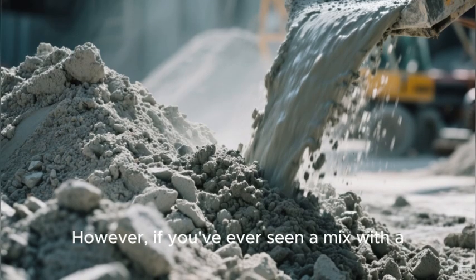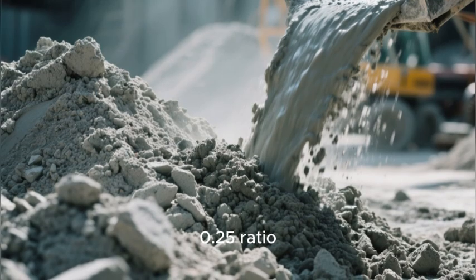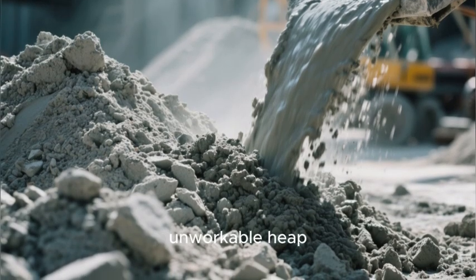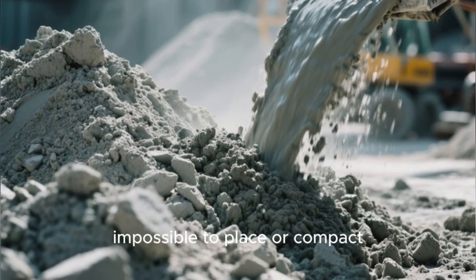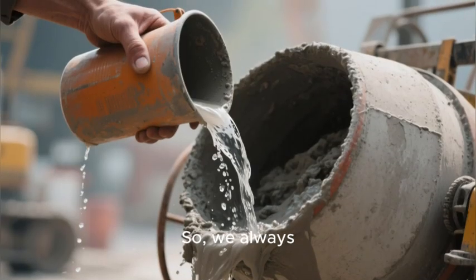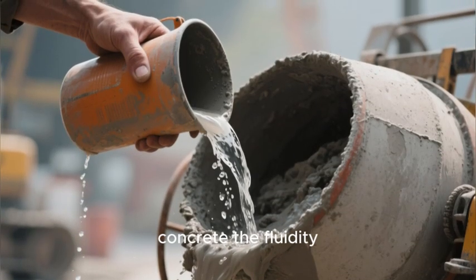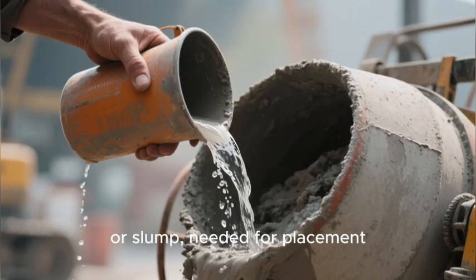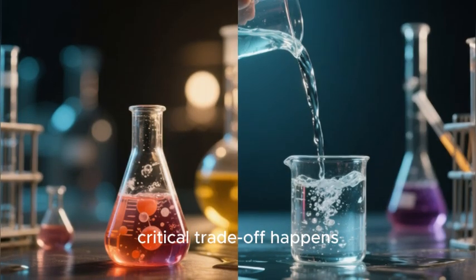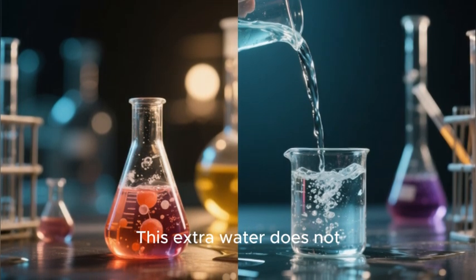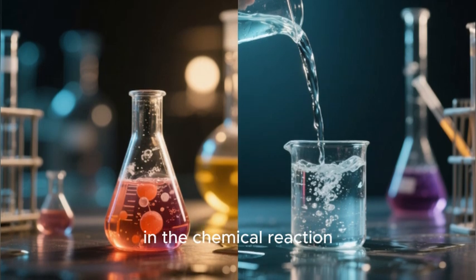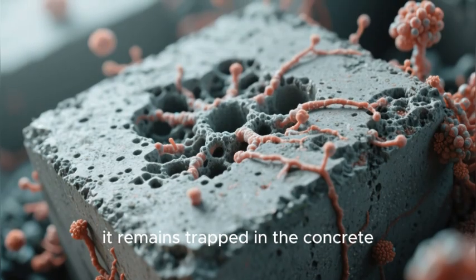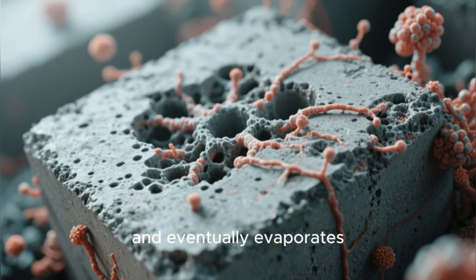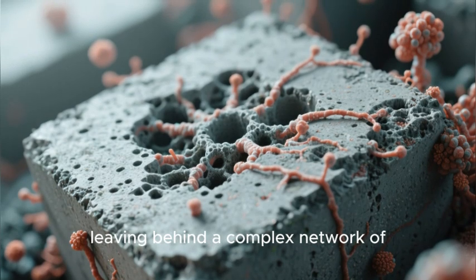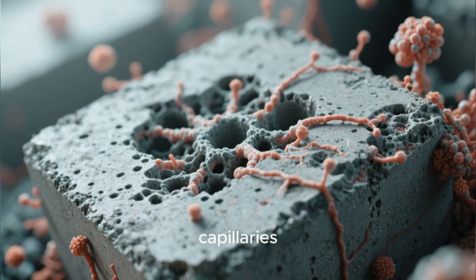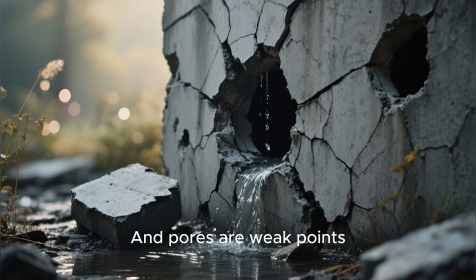However, if you've ever seen a mix with a 0.25 ratio, you'd know it's a dry, unworkable heap, impossible to place or compact. So, we always add extra water to give the concrete the fluidity, or slump, needed for placement. This is where the critical trade-off happens. This extra water does not participate in the chemical reaction. After placement, it remains trapped in the concrete and eventually evaporates, leaving behind a complex network of microscopic pores and capillaries. And pores are weak points.